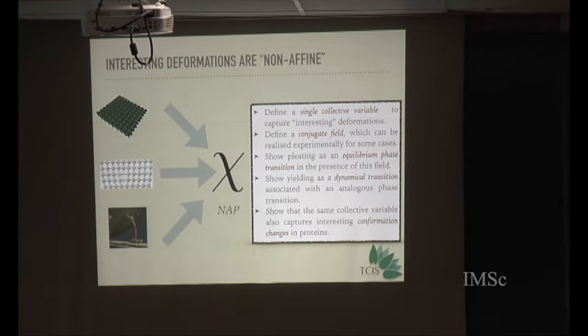So this is actually a thermodynamic variable like any other, and one can define a conjugate field to this variable. And we will see that this is very much like stress, but it's a very peculiar kind of stress. Okay, so once you define this variable and the conjugate field, we will show that pleating of a connected lattice is very much an equilibrium phase transition in the presence of this conjugate field. Okay, so it's not an instability in this case; in the presence of this field, it's a phase transition. And we will show that yielding in solids, normal plastic deformation, is just a dynamical transition which is associated with an analogous phase transition. Okay.